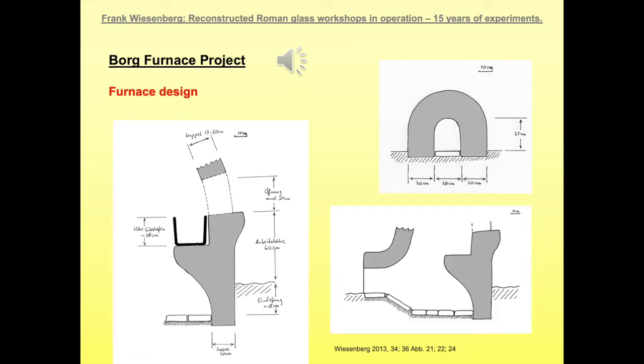Combining this information and keeping in mind that the furnace needs to have a good draft, it's quite possible that the upper end of the stokehole might be a little bit lower than the shelf, which is the support for the glass pots. So you end up with the base layout of the furnace, which you're about to reconstruct now.